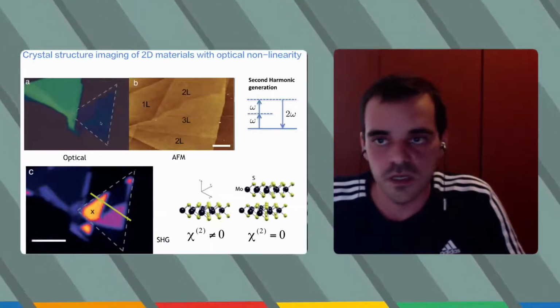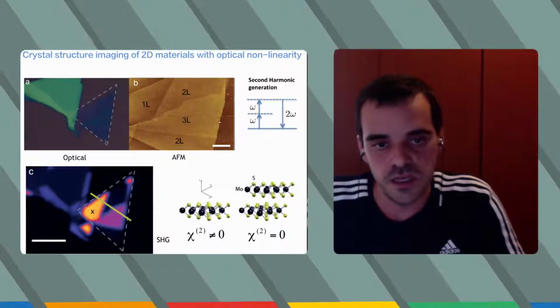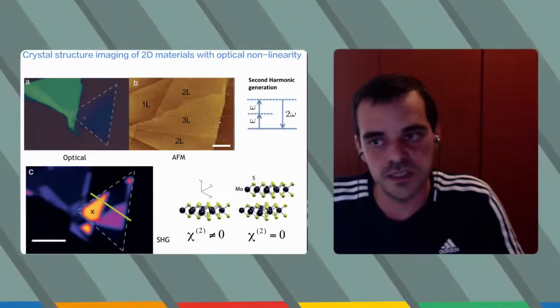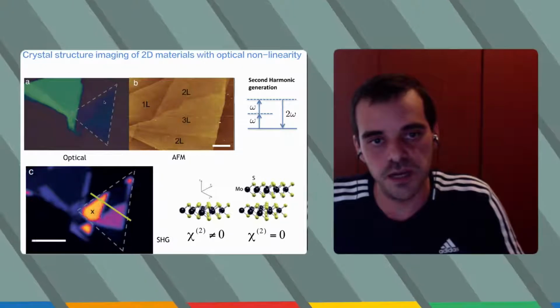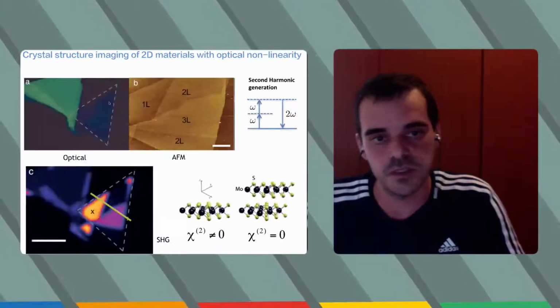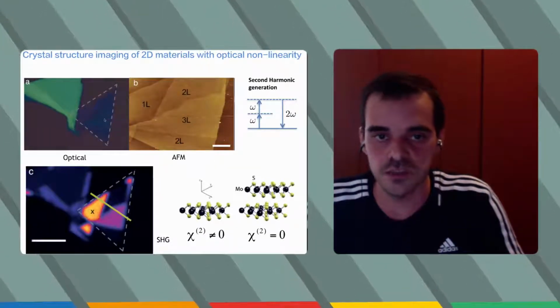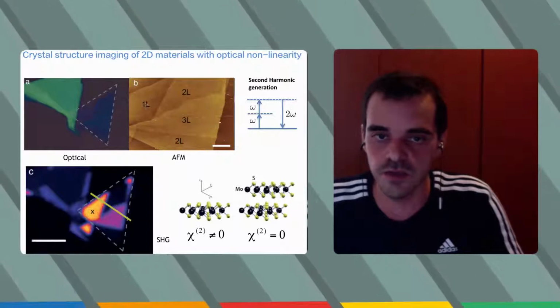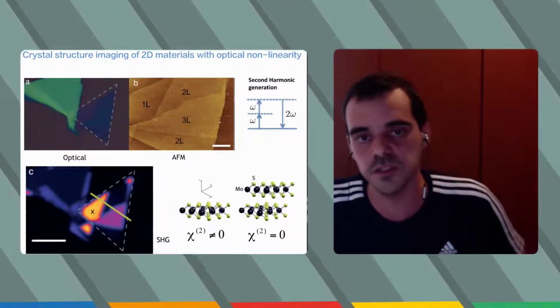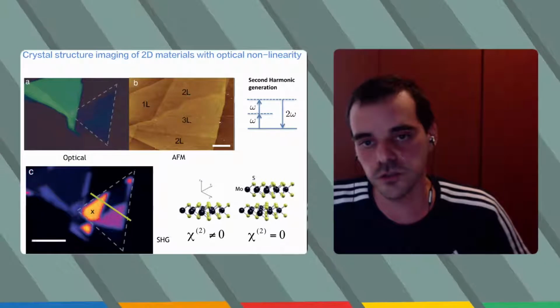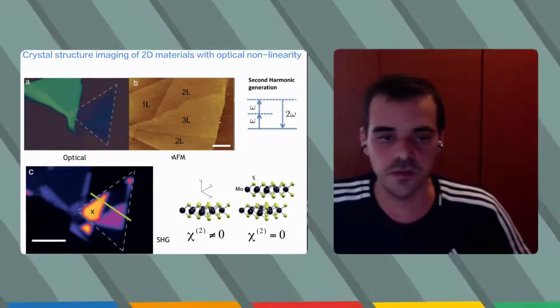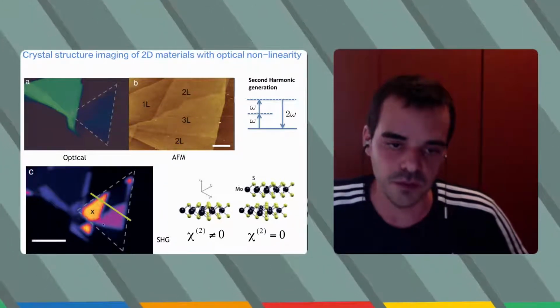In the first example here, this is MoS2. This is a single layer of MoS2. This is a bilayer of MoS2. This is three layers. This is the AFM image, atomic force microscopy image. So this is one layer, two layers, three layers, and two layers. And this is the second harmonic image.